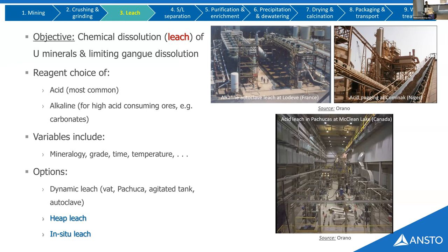You can do a dynamic process in a vat. A pachuca, I think it's a Spanish word, is an aerated tank. You can have agitated tanks and autoclaves as well. I've got heap leach and in situ leach mentioned, but we'll touch on that a little bit later once I've canvassed the conventional process, so you'll be able to see exactly how that fits in. In the photos, the Lodève plant that was operating in France was for alkaline leaching that used autoclaves. Cominak on the right there used acid pugging. You have dry ore, they put acid in and let it cure on a belt that moves it for 3 to 4 hours before it goes into the leach process. And in Canada at McClean, they used the acid leach process in the aerated tanks called pachucas.